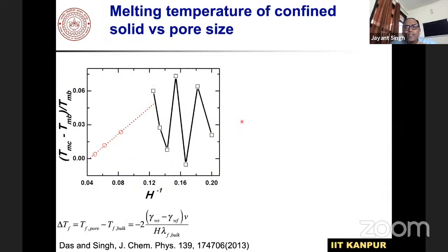So we did extensive simulations. Again, in molecular simulation, we developed a method to calculate the melting point in a confined system. And this is one paper. Of course, we have published many papers on this. But eventually, the story is the following: we show that the oscillatory nature is indeed the case when the pore size is below a few nanometers.